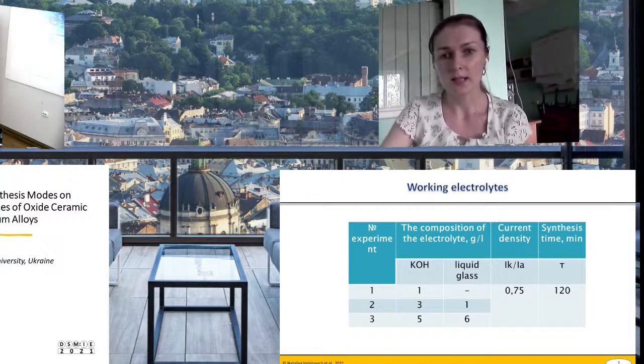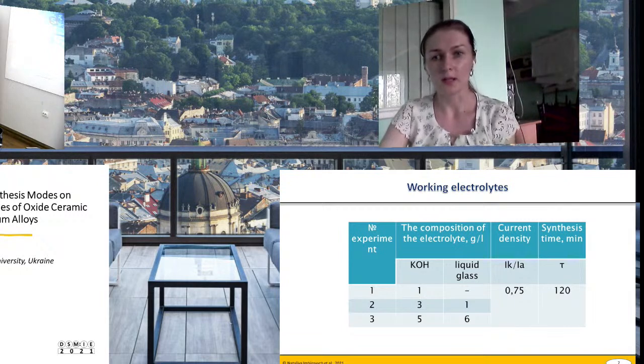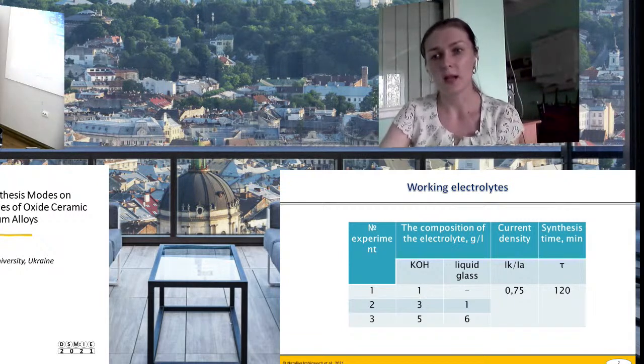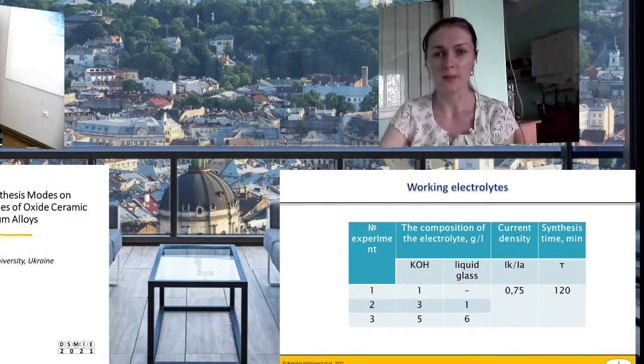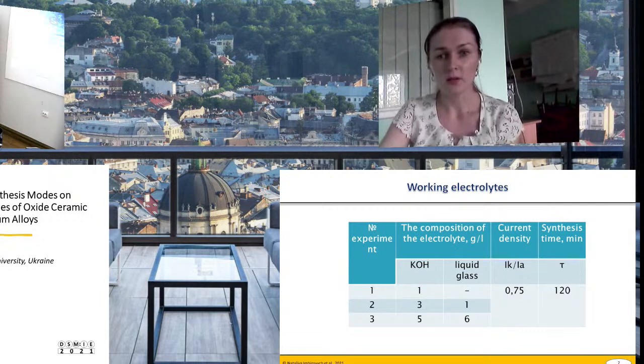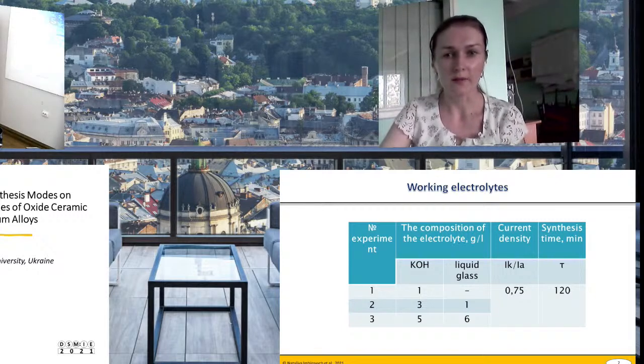It means that the density of anode current was 10 amperes per decimeter squared, and the density of cathode current was 7.5 amperes per decimeter squared. These values gave us the specified coefficient 0.75.